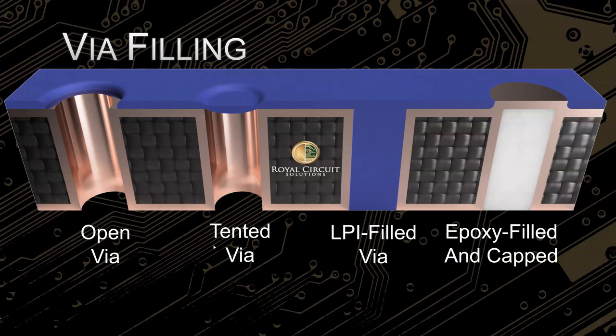All right. I've got another question for you. So when I create my design, let's say I've got a 1/2 ounce copper board, and I'm going to plate 1 ounce copper on it, and I call out a 14 mil hole. Is the number that I give you the finished via size? Do you guys interpret that as the finished via size, or do you interpret that as the hole size, and the via diameter actually becomes smaller? That's going to be your finish size. So if you're calling for a 14, depending on the finish that we're using, we're going to go up 4 to 5 mils bigger than that. We're going to drill a hole larger and allow for the plating tolerance to finish at your requested size.